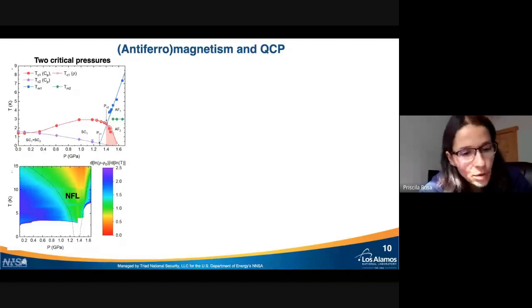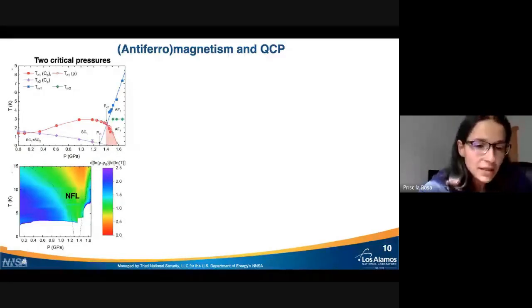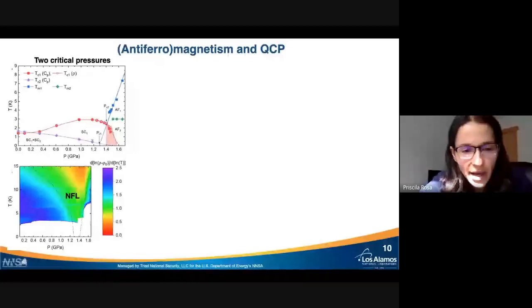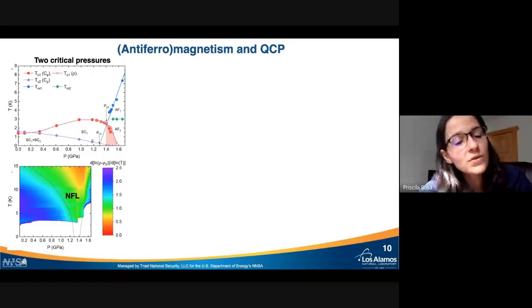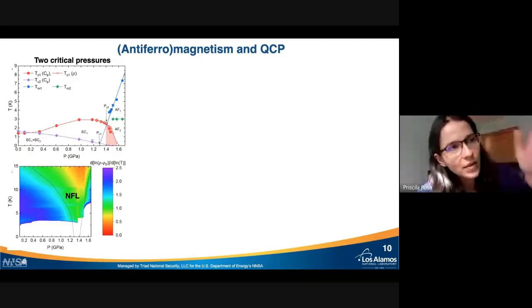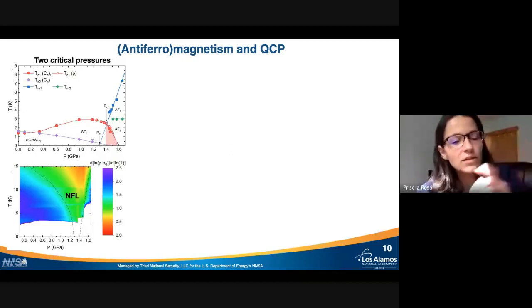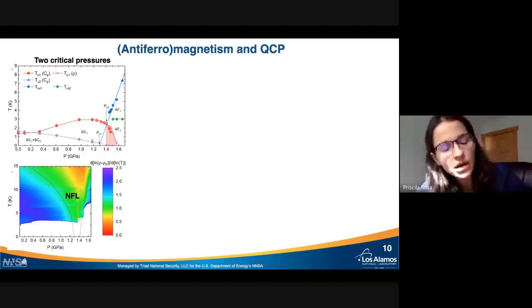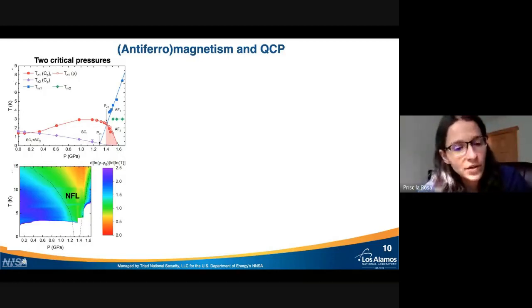And close to this quantum critical point, indeed, we can see something that resembles a non-Fermi liquid behavior. So for a Fermi liquid here on the left, we expect a T-squared behavior of the resistivity. Close to a quantum critical point that may not hold anymore, and in fact, we see something that's close to being linear. Unfortunately, starting at 15 Kelvin or so, we start seeing the tail of that peak at higher temperatures, so things are not so reliable. Unfortunately, we cannot extract an exponent over a decade in temperature. But it's pretty clear that things